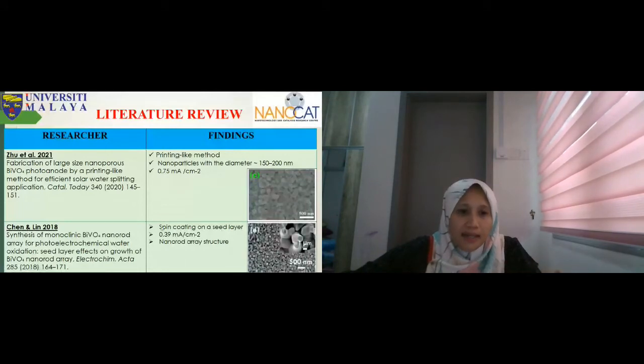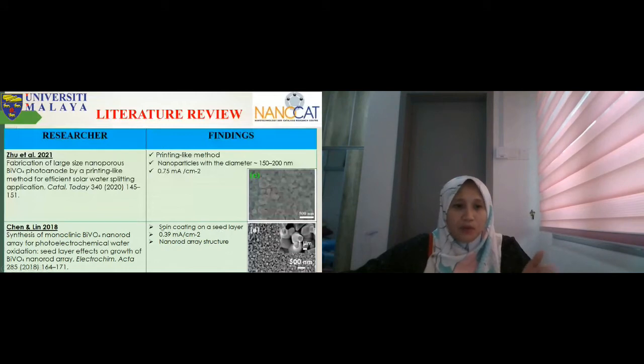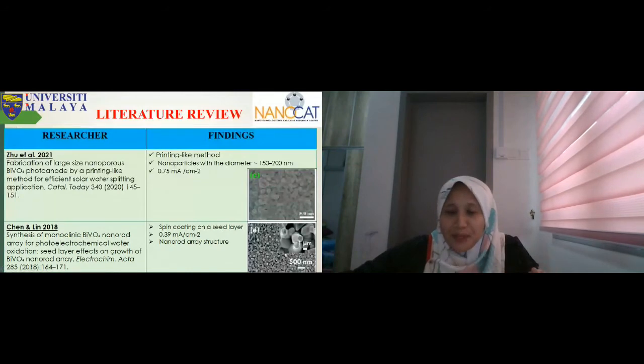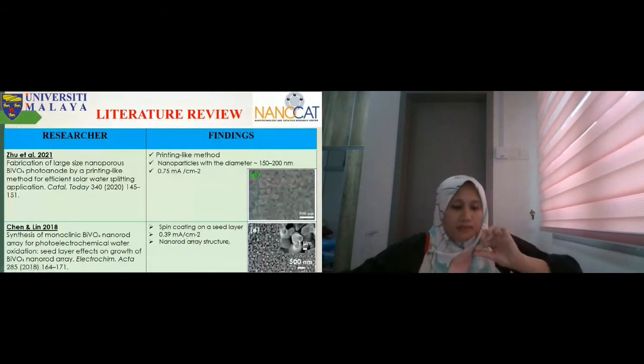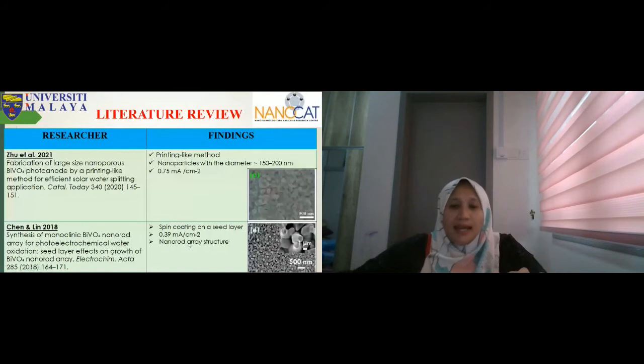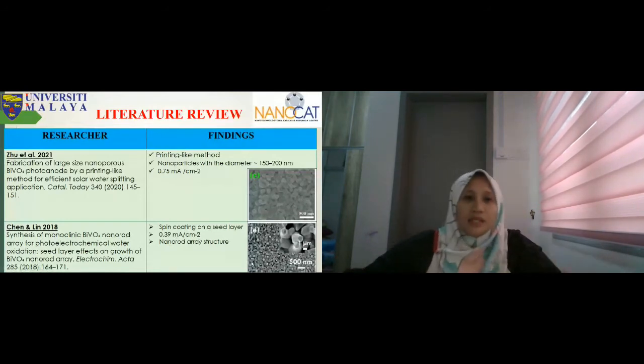The next is by Chen & Lin 2018, published in the Electrochemical Acta journal. He used monoclinic bismuth vanadate nanorod arrays for PEC water oxidation, and he studied the seed layer effect on the growth of the BiVO4 nanorod array. Here we can see the beautiful BiVO4 nanorod structure. In this case he used spin coating as a thinner layer on a seed layer, and the current density they get is 0.39 milliampere. This looks like a nanorod array structure.